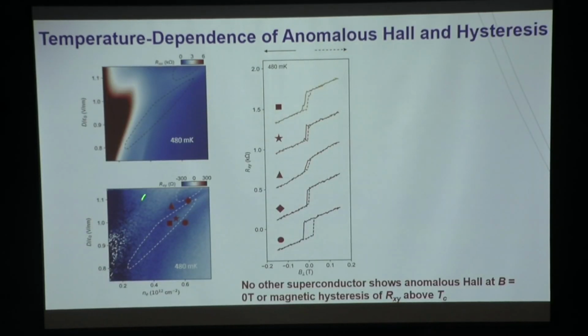Okay? And this is above TC. You see this dashed line here outlines the SC1 I was showing you. And interestingly, even above TC at 480 millikelvin, you have anomalous Hall signals inside this big oval here, both inside and outside. Okay? So the star and the square positions are both inside SC1. When you scan out-of-plane magnetic field, you get this jump in Rxy, and you get a hysteresis loop. And this is absent from any other superconductors, as far as I can tell, from literature.